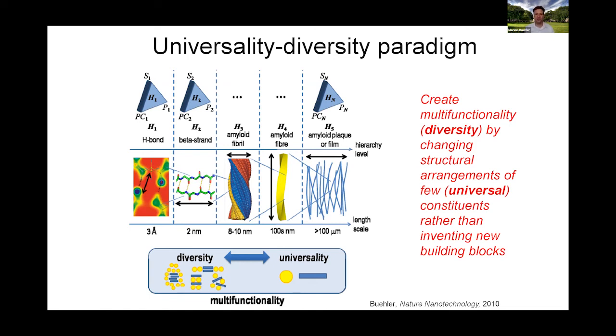So what happens when you have a composite like in the conch shell is you have a different paradigm. You don't avoid the creation of these damages at all. In fact, you allow that, you welcome the damages. But what you do is you create weak paths and you force the crack to dissipate energy in many different directions. You imagine having a brick and mortar structure. Every intersection between the bricks and the mortars is an interface that can break more easily.